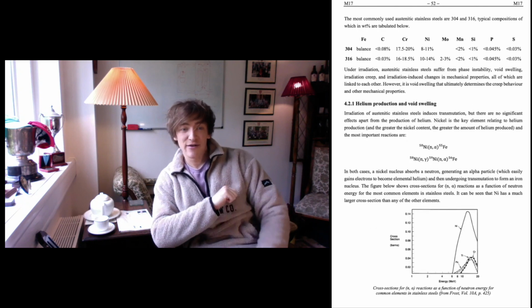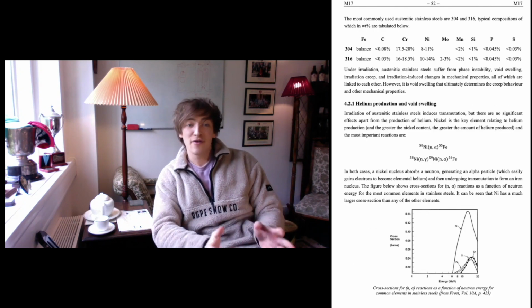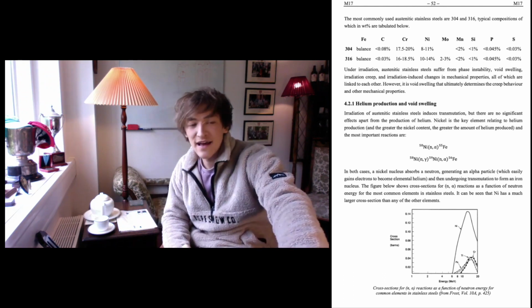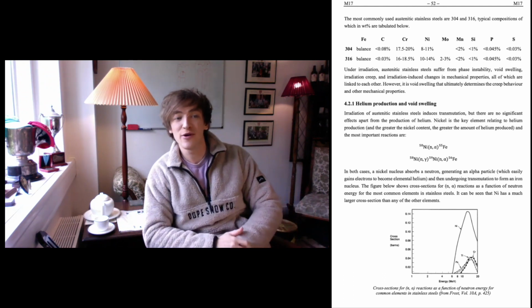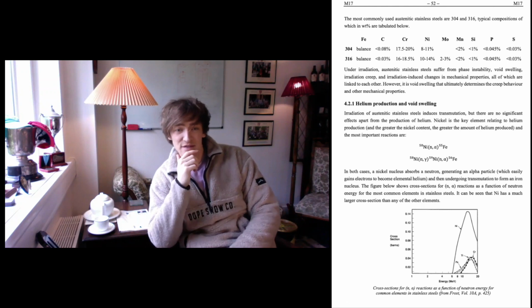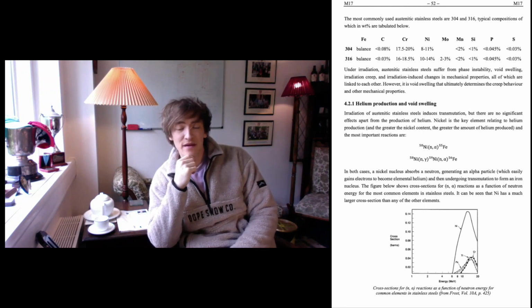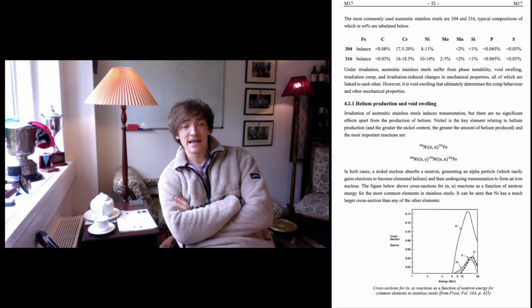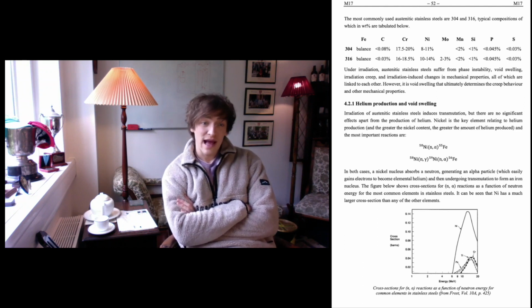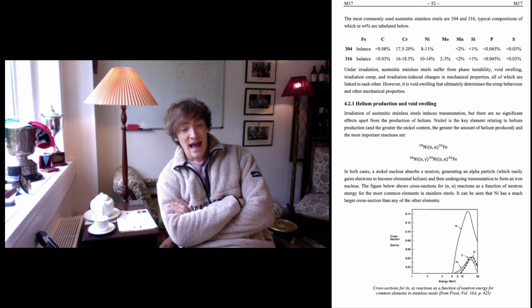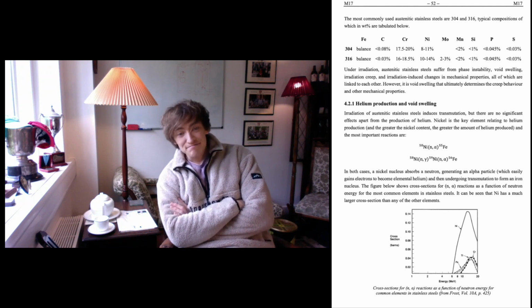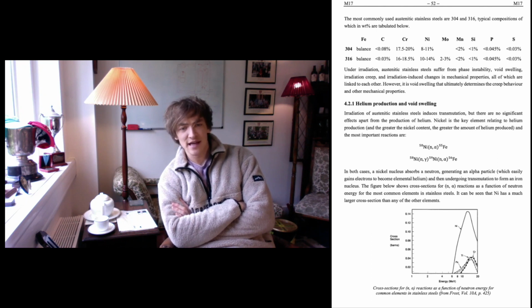Fortunately for the metallurgists, however, you will know already the most commonly used alloys, 304 and 316, the composition of which I've shown you in this table. The main challenges for these alloys as cladding are phase instabilities, void swelling, creep, and mechanical property changes. And unfortunately, all of those are interlinked. However, it's swelling really that is the main concern with stainless steel cladding.